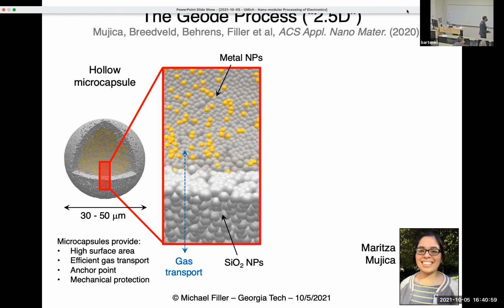And having this porous wall is really important because it allows gas that we use to grow the nanowires to transport from the outside to the inside, to grow nanowire crystals inside our micro geodes. Okay. I say up here, you can barely see it. It's 2.5D processing. So it's not quite 3D, but it's still on a surface. But it's a very high surface area, right? It's important to keep in mind.